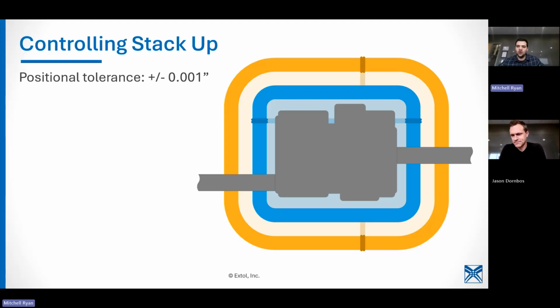Yeah. And the best way to remove mold release for this process, I don't know if I have a great answer for that, but maybe somebody else on the call does. If somebody knows the answer to that question, type it into the chat. How do you remove mold release from a plastic part? And really, it's more about just trying to get it off of the edge or remove any concentration of it from the weld rib, which is more minimizing impacts, because there are applications we do with mold release on the parts, which is pretty typical. It's a contaminant, so the less you can have on the part, the better.